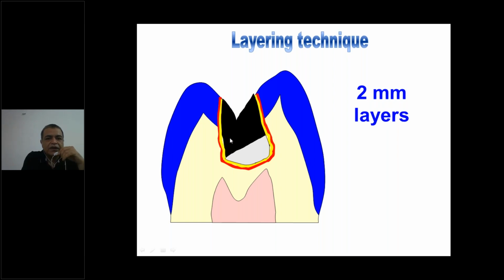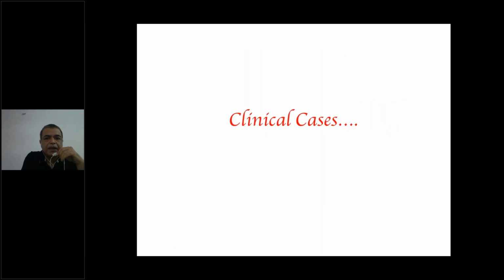If this was a single increment like this, I will have 1, 2, and 3 bonded surfaces and only 1 unbonded surface. So my C factor goes higher and the longevity of my restoration goes down. Whereas if I put it in oblique layers, now I have 1 and 2, only 2 bonded surfaces and 2 unbonded surfaces. So my C factor has halved, and the longevity of my restoration will have much more chances. So this is how it happens.